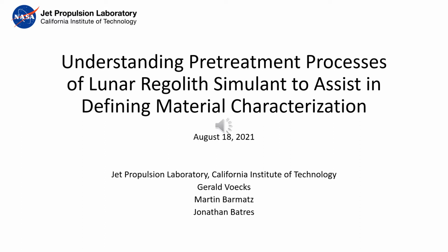Approximately 20 grams of simulant is placed in a quartz tube, 12 millimeters ID, which is subsequently placed in a radiant heated furnace and attached to a vacuum system capable of 10 to the minus 5 torr. While under continuous vacuum, the material is heated at a 2.5 degree centigrade per minute rate to an elevated temperature, while simultaneously monitoring volatiles produced over the course of heating. Pressure variations were monitored to correlate with time, temperature, and volatile species during the test period.